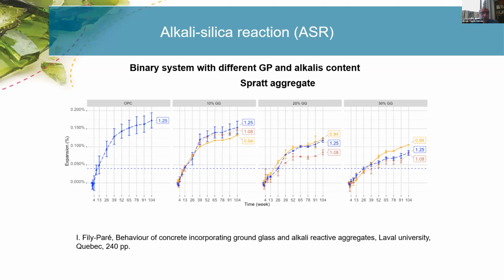Now, yes, ASR is another story. Many people are asking about ASR because we have 13% or more, and now the new standard in Canada allows up to 15% of alkali, because this is the case of glass. But you can see here that when we add from 10 to 30% of glass pozzolan, the expansion is decreasing, and we worked with a very reactive material, which is a Spratt. Actually, we are working with an average reactive aggregate or borderline aggregate. This work is done by Isabelle Fily-Paré together with Benoît Fournier and José Duchesne from Laval.